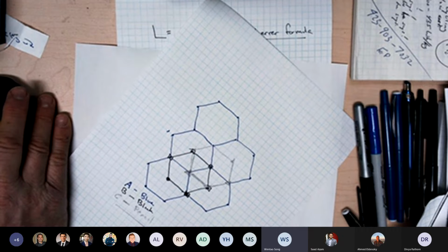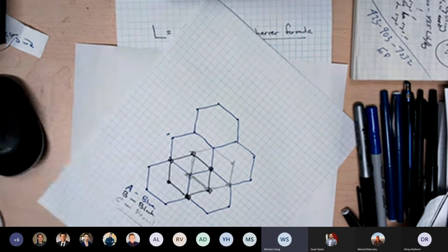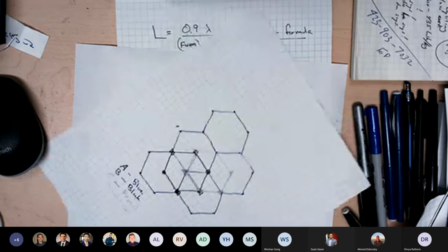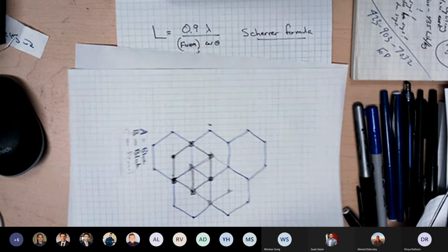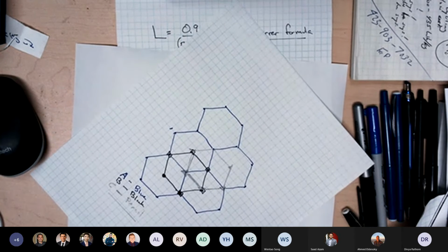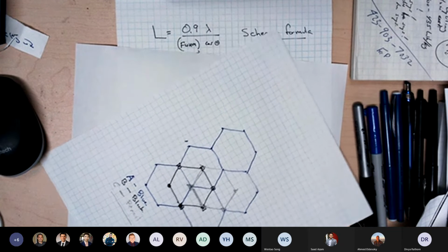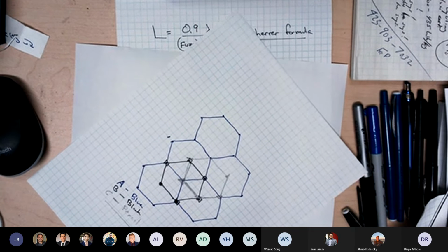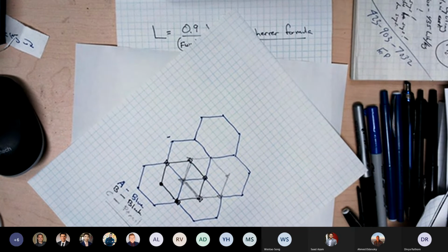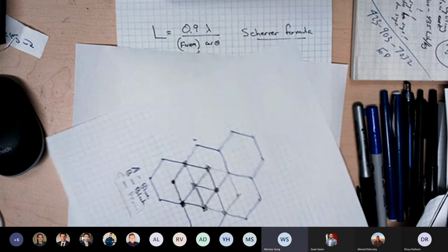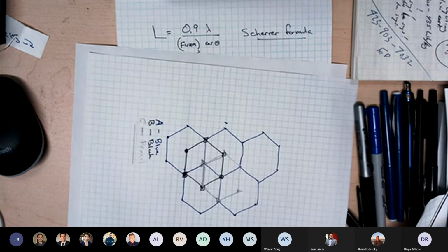I understand the question. The thing is that the temperatures that you need to cause these sheets to rotate during graphitization are temperatures over 2,000 degrees C. I see. So the kind of temperatures that we can access in the battery, you know, maybe we can go to 70 degrees, 80 degrees C. It's just so trivial compared to what you need to cause these things to rotate. I see. That makes sense. Thank you. Yeah.